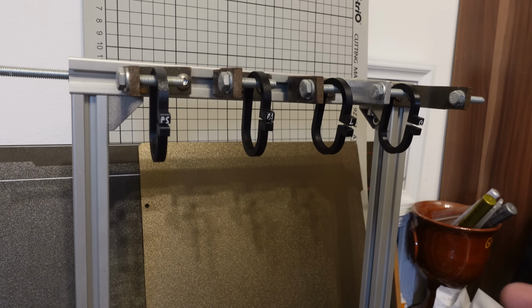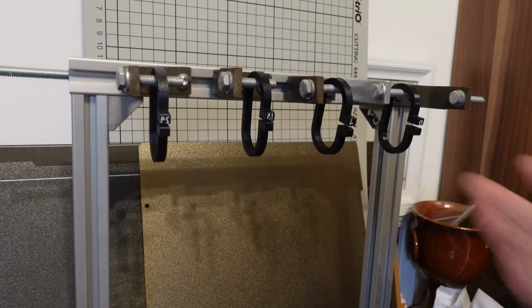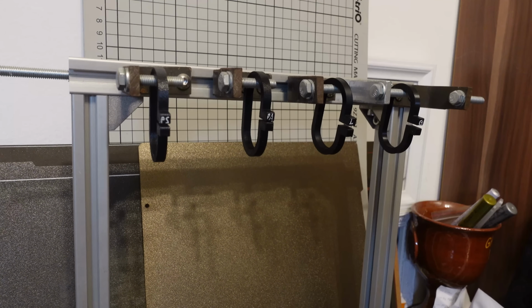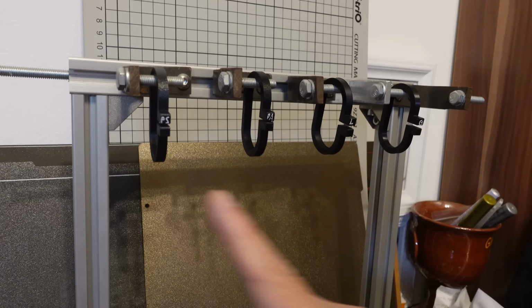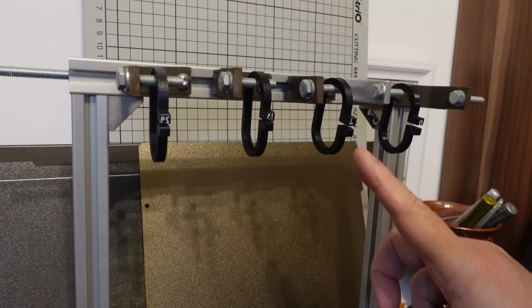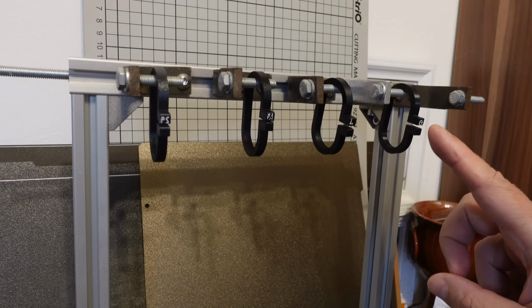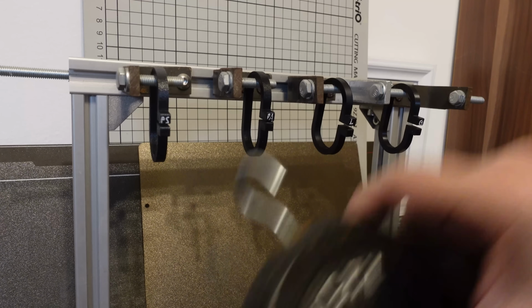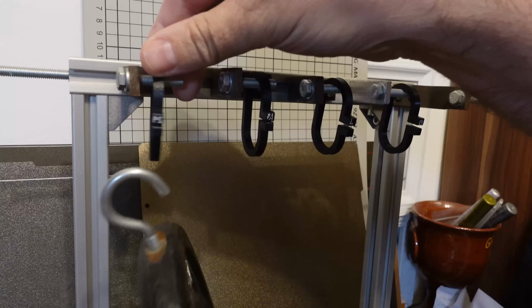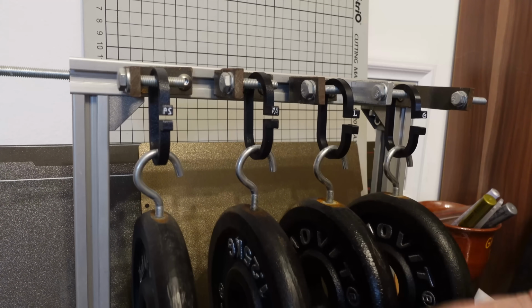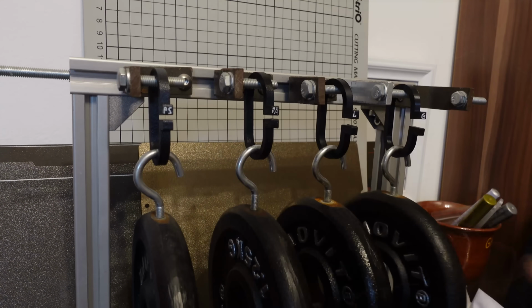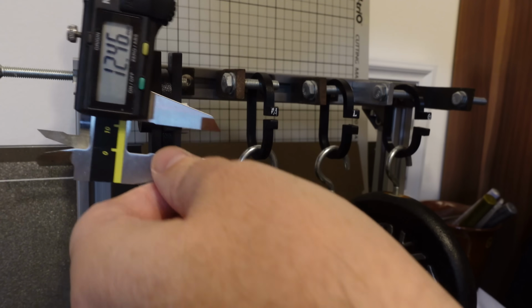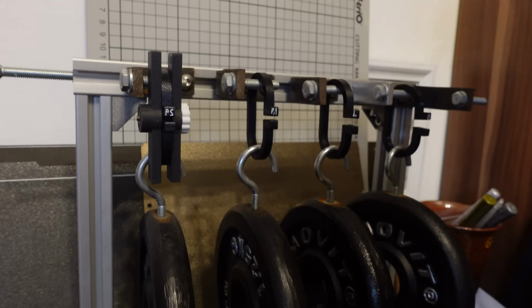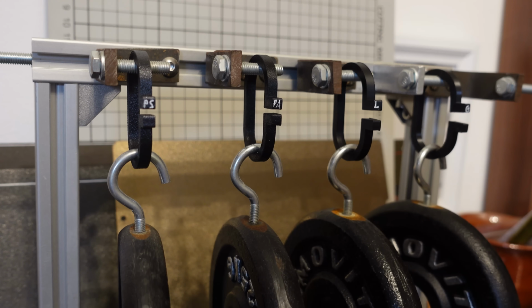The creep test measures the deformation under constant load, and I have several tests in progress, this time all black filaments: PPS-CF, PET-CF, graphene reinforced PLA, and graphene reinforced PETG. The load is 1.25 kilograms. Interesting, surprisingly small start deformation on these two. 12.46. They will be measured every day, but in the video let's jump in the time.